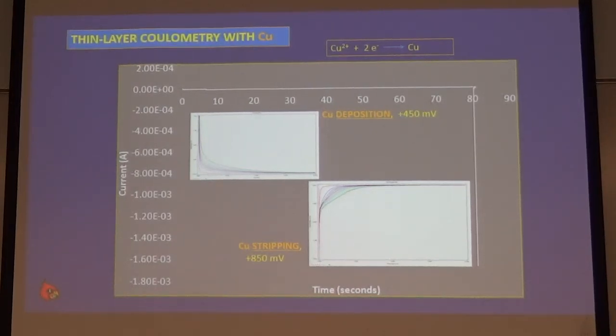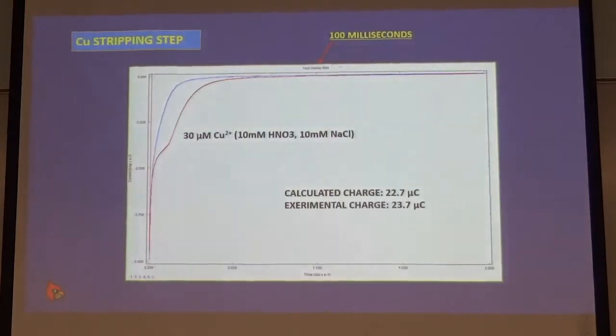So when you're dealing with a metal, you've got this deposition stripping issue that you have to understand. If we look at that stripping signal really closely, now you can see the time scale. This is 100 milliseconds here. The blue trace is what we get when we put in a blank solution that has no copper in it. You still get some current.